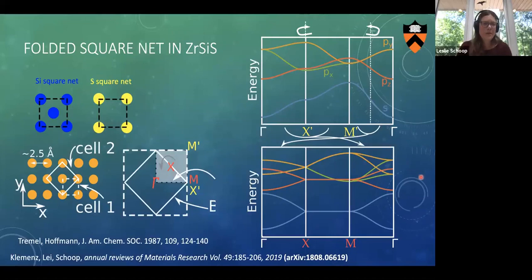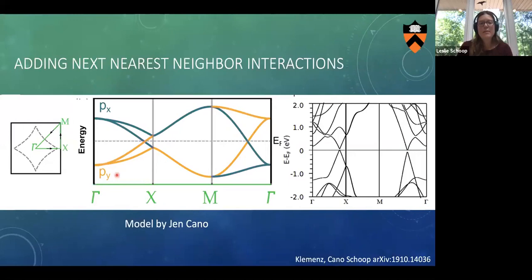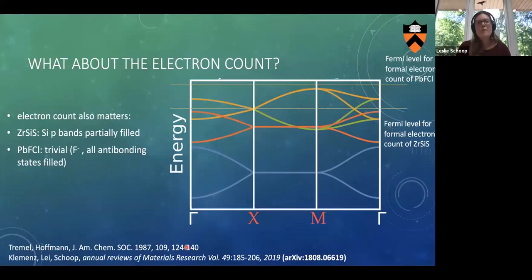So here's a bit better tight-binding model. If you include some next-nearest-neighbor hopping and only look at px and py orbitals at the center square net, and this is just a comparison to DFT, you see that there's a remarkable agreement. Okay, but I just wanted to point out that we need both: 2 atoms per unit cell folds the band structure and we get the crossings. But it doesn't pin our Fermi level at the right position. There are many materials in these crystal structures with side-centered square nets where the Fermi level is just up here. And so we can use electron counting, like PbFCl as an example, and if you would count it, you would count to 8.